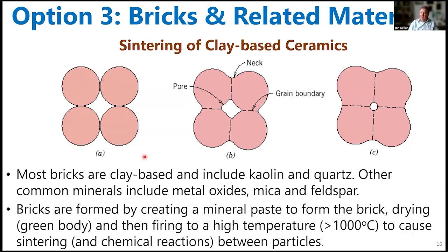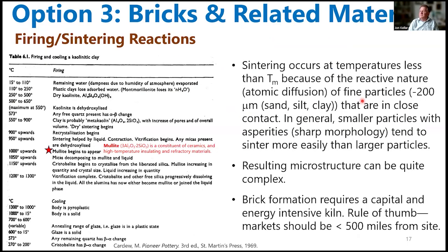It's allowed to air dry, giving what we call a green body, and then fired at a high temperature, generally over 1,000 degrees Celsius, to cause sintering between particles. And this graphic above is showing the sintering process. These are the individual starting particles in the green body. We go above 1,000 degrees Celsius, and the sintering process is a diffusion process between adjacent particles, and it happens at less than the melting temperature to give a consolidated body. And that is described here and shown by this old graphic.